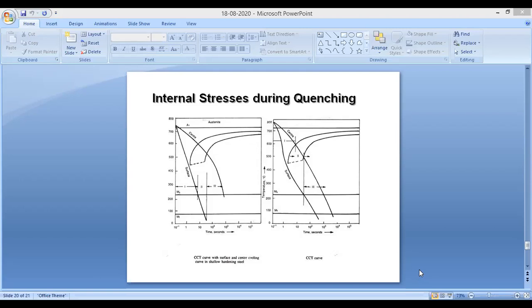Increasing carbon and alloying elements lower the temperature and make the steel more prone to quench cracking. The presence of high carbon not only aggravates this by lowering the temperature but also increases the brittleness of martensite, increasing the tendency to quench cracking. If the time of holding the quenched steel part between room temperature and 100 degrees centigrade is increased, then the quench crack tendency increases. The probable reason is additional strain produced due to formation of martensite by isothermal transformation of retained austenite.